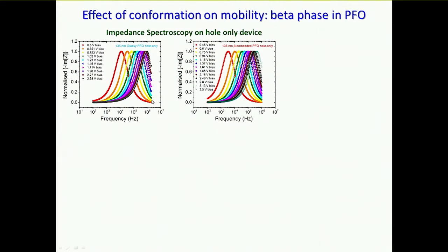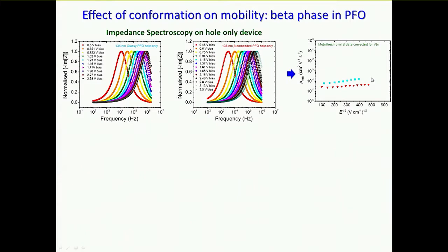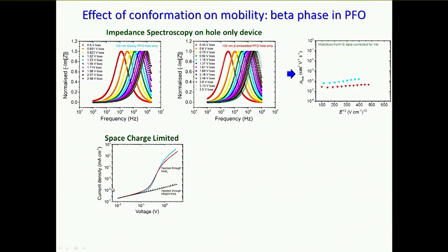So we also looked at the mobility with impedance spectroscopy. You don't need to pay very much attention to these graphs here, which are showing the electrical response in frequency space, but the point is those data look actually quite similar. And when we extract a mobility from them, we find, okay, for this approximately quasi-steady state measurement, the mobility has been reduced by introducing the beta phase, but not by so much. We did another kind of steady state measurement using space charge limited current transport. Again, we find the same, the mobility or the conductivity is reduced, but not by so much. Okay, so in this case, the effect of beta phase is not so bad.